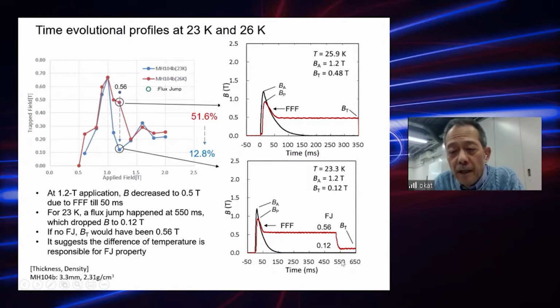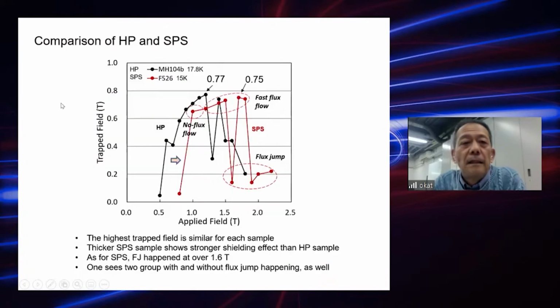And for 23 Kelvin, a flux jump happened very, very lately at 550 milliseconds here, and which dropped the trapped field BT to 0.12 Tesla. So it is what's a pity. It suggests the difference of the temperature is responsible for the flux jump property and occurrence. So then, just before the flux jump occurred, the trapped field remains 0.56 Tesla. That means here. So then it is very, very important to suppress the flux jump occurrence anyway.